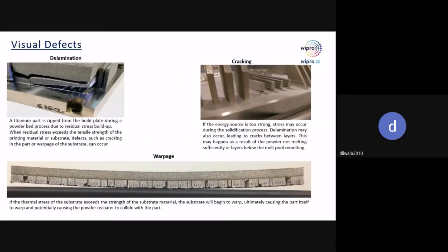Delamination. When the residual stresses exceed the tensile strength of the printed material, this sort of delamination or heavy warpage or distortion will occur on the parts. This is delamination. This is cracking. If the energy source is too strong, then stresses will occur during the solidification process, resulting in cracking.